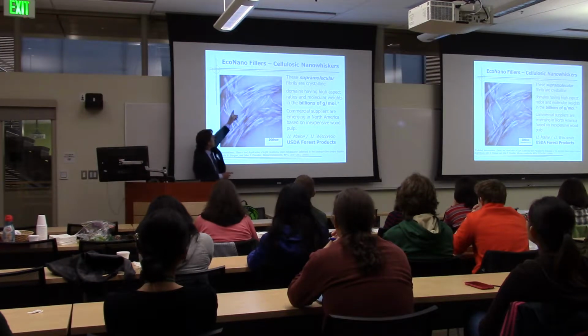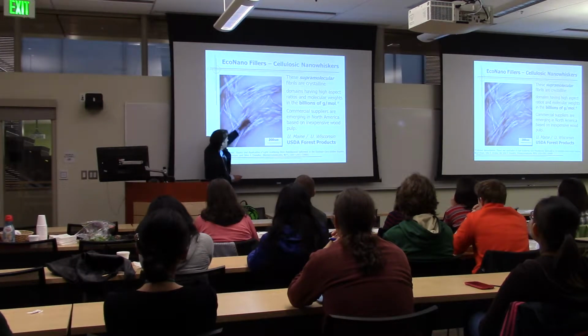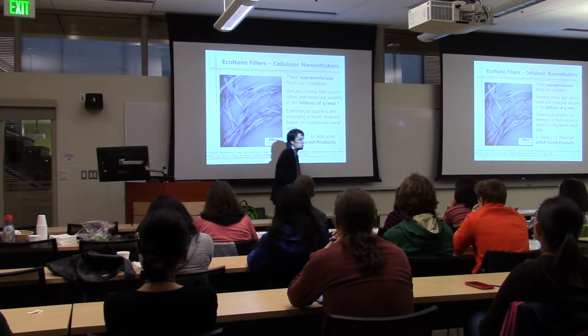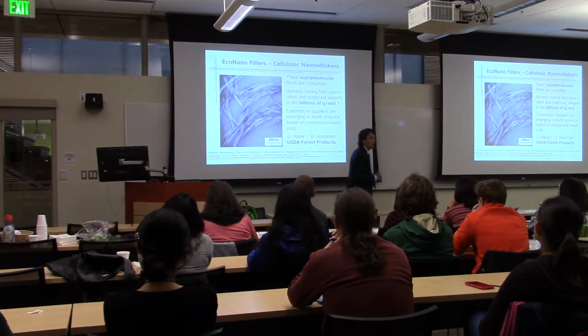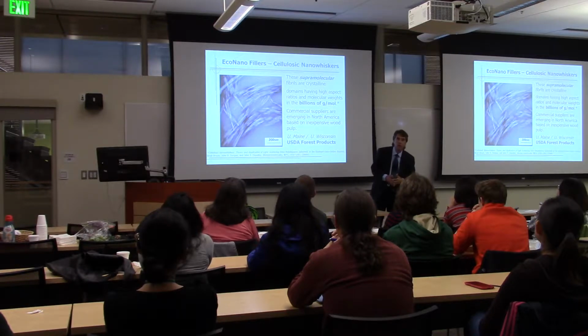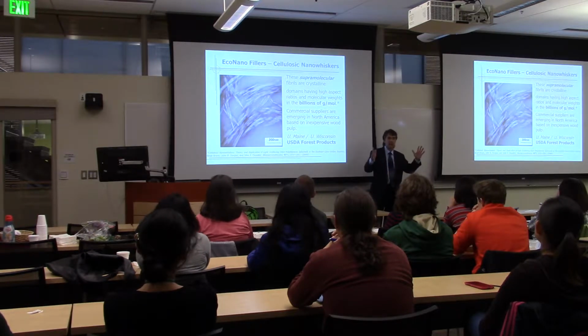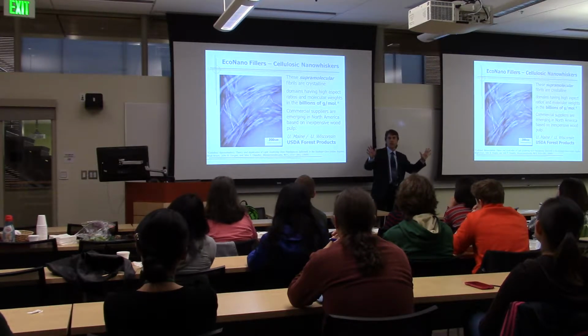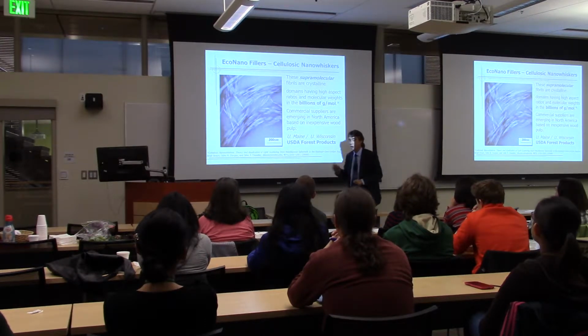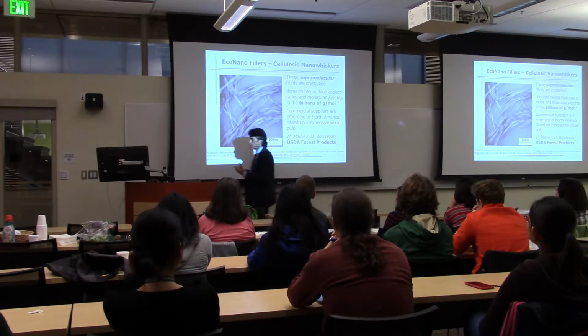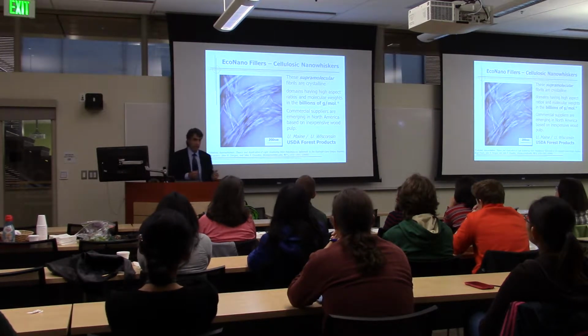But if you look at the individual fibrils that are there, you can see this is 200 nanometers. So you can get things which are 200 nanometers in length and maybe 10 nanometers across, or even 5 nanometers across. And in composites theory, the aspect ratio of your fiber really makes a huge difference. Okay, and so these are high aspect ratio renewable fibers, but they're available at the nano scale.